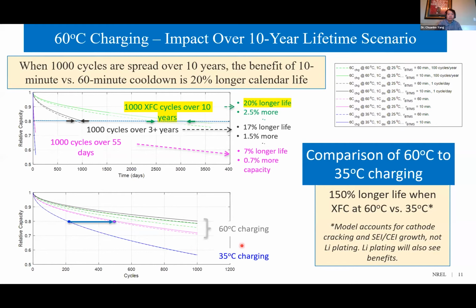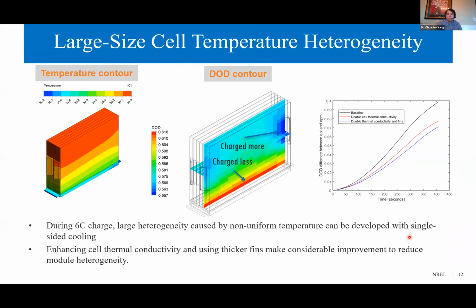The model estimated 150% longer cycle life when charging at 60 degrees Celsius compared to fast charging at 35 degrees Celsius. It's worth mentioning the model accounts for cathode cracking and SEI growth, not Li plating. We also see benefits. As mentioned before, Li plating can be provoked with heterogeneity. Heterogeneous behavior becomes significant for large size cells.